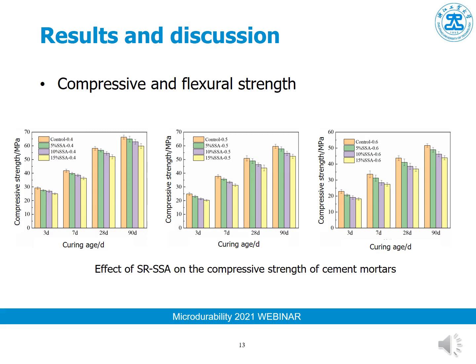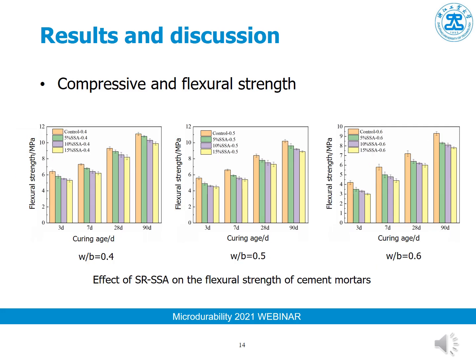This is the test results for the compressive strength tests, and we can see that with the addition of sewage sludge ash, the compressive strength of the cement mortar is reduced, and more ash caused more strength reduction. And it is the same result for the flexural strength tests. More sewage sludge ash results in more flexural strength reduction. So when we recycle this kind of ash in cement-based materials, we have to take care of the strength reduction.